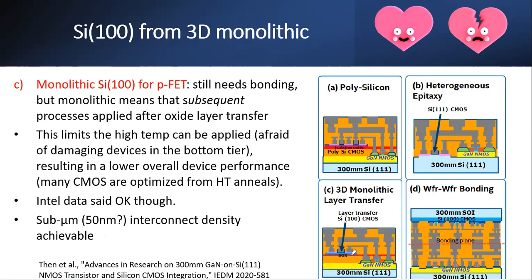silicon. That's fine, except one thing. You cannot have too high a temperature. You have to avoid your process, if it demands a high temperature, hurting the gallium nitride below. All right. That's the only key concern. Is that true or not? That's difficult to say. But Intel data said, yeah, okay. Well, that's interesting. I would say that's interesting.